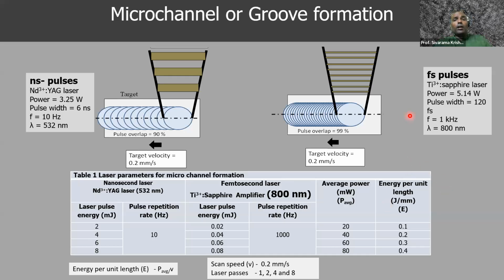Okay, so the way in which microgrooves are formed, essentially using these laser pulses, is nearly identical. But just to recap what we are doing, we move the sample at a certain velocity. In both the nanosecond and femtosecond case, the target velocity was kept identical. The nanosecond laser was fired at 10 hertz. It was 6 nanosecond pulses, albeit at a green wavelength, 532 nanometers. In the femtosecond case, we used titanium sapphire laser pulses, but these fired at 1 kilohertz and pulse width was about 100 femtoseconds. And we scanned the stage at similar speeds.